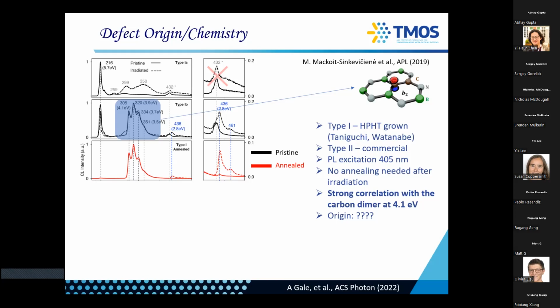The theory suggests that it's just a carbon dimer sitting in a boron nitride lattice, which makes a lot of sense because carbon is basically the same size as boron and nitrogen. So it's interesting that when you take this type of material and you irradiate with electrons, right? So the dashed line is irradiated, you do create our 436 nanometer emitters. Okay, so in the carbon HBN that contains carbon dimers, we always create these defects.